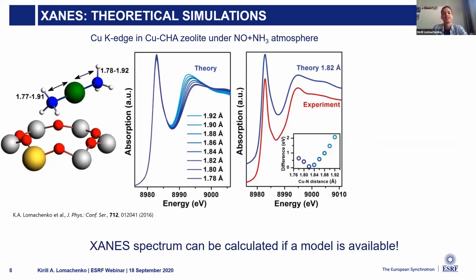Another good thing about XANES is that XANES spectra can be calculated. So if you have a model deduced from a theory, from a DFT calculation, from electrodynamics, or from some other structural sensitive method like X-ray diffraction, you can calculate XANES spectra and determine local structural parameters by comparing the experimental spectrum with the theoretical spectrum.